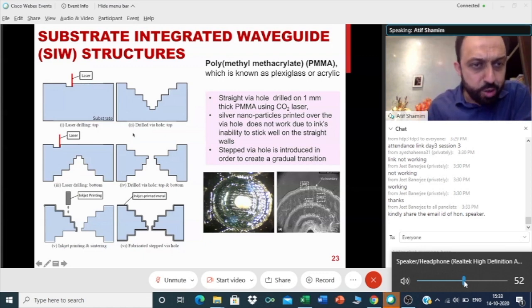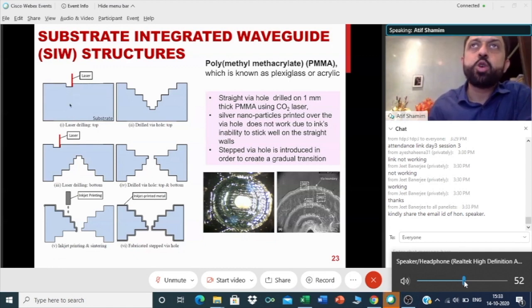So what we did first, we took a thick substrate, like a 1 mm PMMA, and in order to connect the top and the bottom, we created a hole. First we created a straight hole through laser and then tried to print it. This was 1 millimeter, and remember, one printed layer gives you about half a micron of thickness. So we tried to print it, but the ink was not sticking to the vertical walls. And we needed hundreds and hundreds of layers to print it. So it was very troublesome.